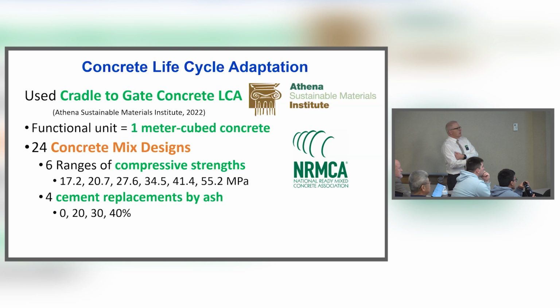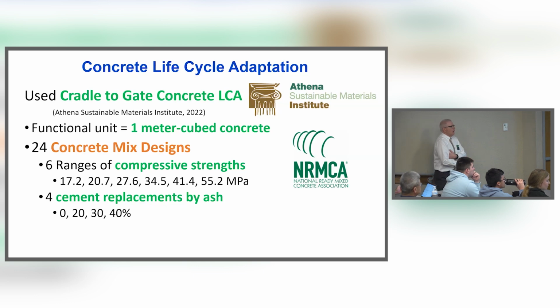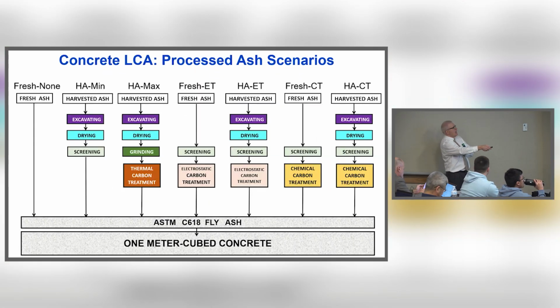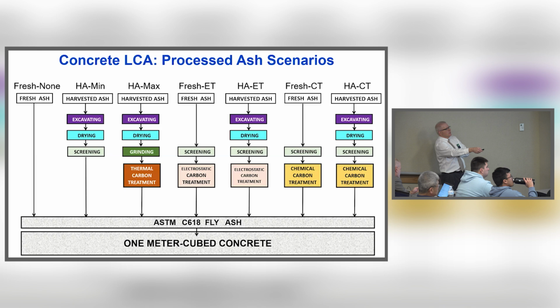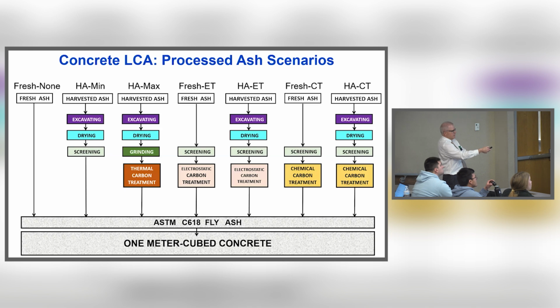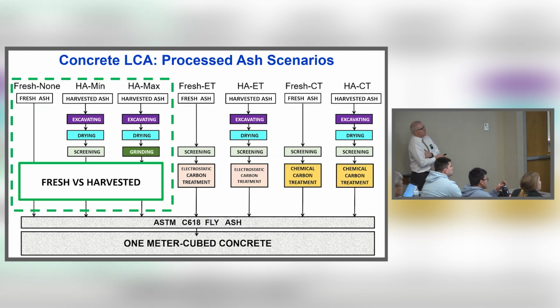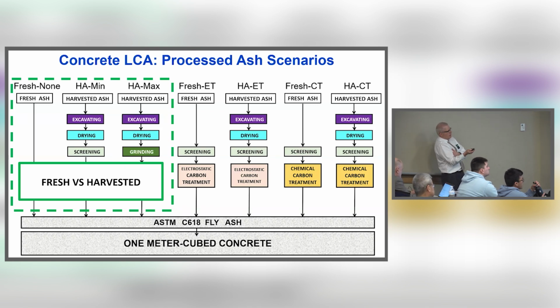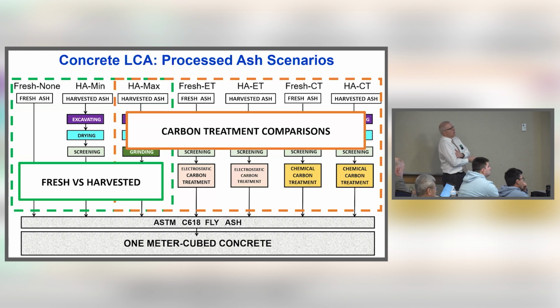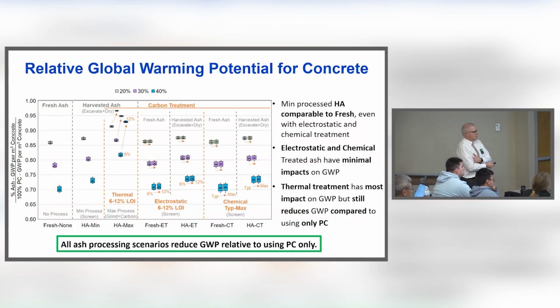And then we looked at 4 different levels of cement replacement, from none, no ash, up to 40% of the cement being replaced with ash. And we looked at producing 1 meter cubed of concrete. We looked at essentially using fresh ash alone, harvested ash with minimum processing, harvested ash with maximum processing. And then I looked at different carbon treatment scenarios: fresh ash with electrostatic treatment, harvested ash with electrostatic treatment, fresh ash with chemical treatment, harvested ash with chemical treatment. We just stepped through these different processes, looking at all the different unit processes to create 1 meter cubed of concrete. So this was fresh versus harvested on the left, just comparing them 1-to-1, and then looking at different carbon treatment comparisons. This is what we get, another busy graph.